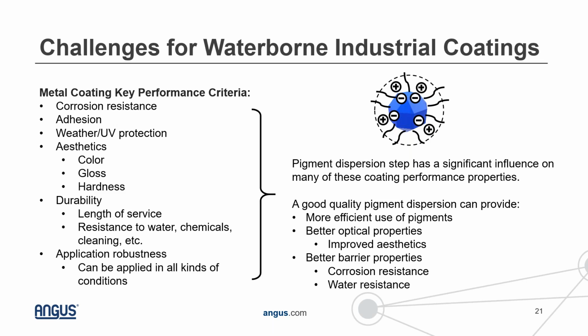You also want to make sure that there's application robustness, right? Especially for coatings that are applied outdoors, you want to make sure that even if it's a humid day, you're still getting good film formation. Or even if it's applied shortly before a rainfall, that coating is still going to adhere and cure appropriately to that metal substrate. And pigment dispersions have a very important influence on a lot of these properties. A good quality pigment dispersion can provide not just a more efficient use of the pigments, but also better optical properties, which can lead to better aesthetics. It can also lead to better barrier properties, which can improve things like corrosion resistance and water resistance. So the pigment dispersion step is a really critical step for making sure that you're able to hit these different performance features in waterborne industrial coatings.